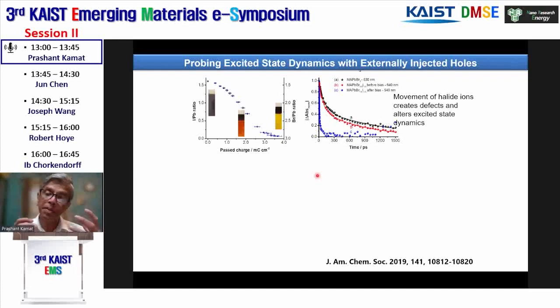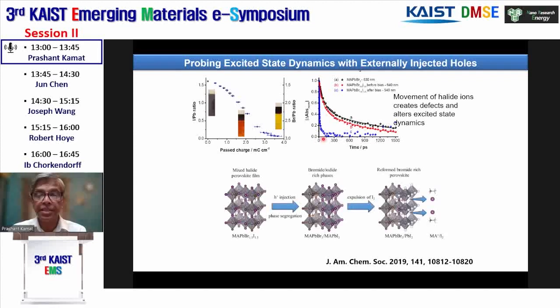Interestingly, it also changes the defects and the other recombination. So we can follow the bromide and iodide emissions that we see before and after bias, the red and the blue. So this is before bias and this is after bias. So there is a change in the excited state.